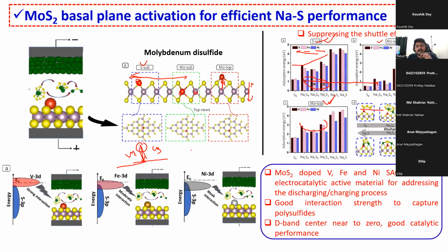Why? Because there are two kinds of molecular orbitals: bonding molecular orbitals and anti-bonding molecular orbitals. If this is the Fermi level, the bonding molecular orbitals will be around here, and they will be completely filled. The anti-bonding molecular orbitals are the ones near the Fermi level. That's why we use the d-band center as a descriptor for understanding the catalytic performance, because the d-band center of the transition metal is closer to the anti-bonding molecular orbital. If we know where the d-band center is, we can know where the anti-bonding molecular orbital is, because the bonding molecular orbital is already filled. We cannot fill that. We need to fill the anti-bonding molecular orbital. If the anti-bonding molecular orbital is very close to the Fermi level, it can easily be filled.